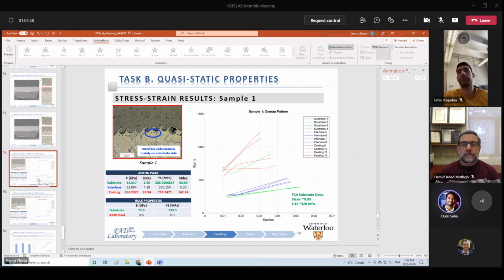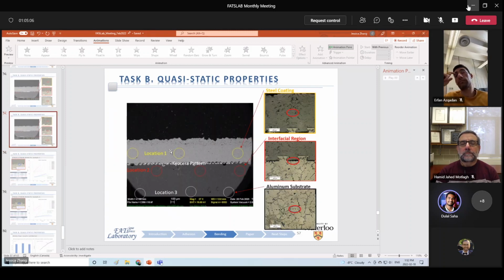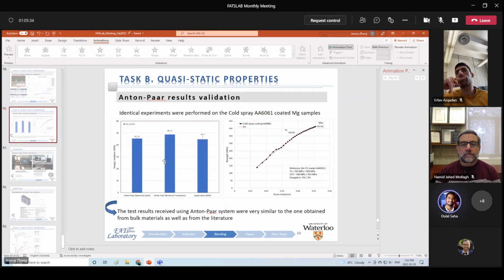Okay, so as our coating thickness is around 200 micron, we cannot produce any micron-size or sub-size sample for real tensile testing. That's why, in order to get properties like the yield strength and the elastic modulus of the coating, we did cyclic indentation here. And before that, we matched this elastic modulus for the coating and substrate with other material, like on the magnesium substrate here.